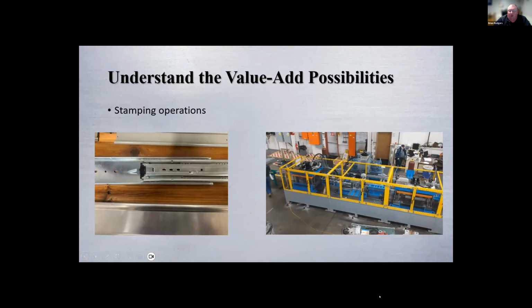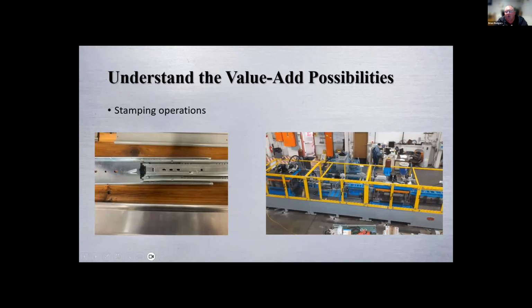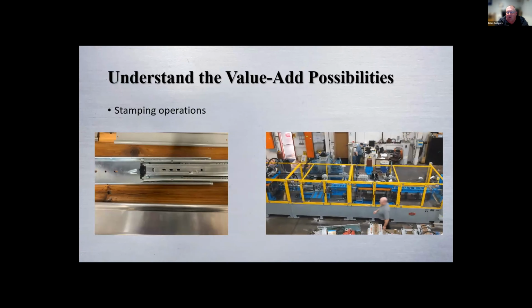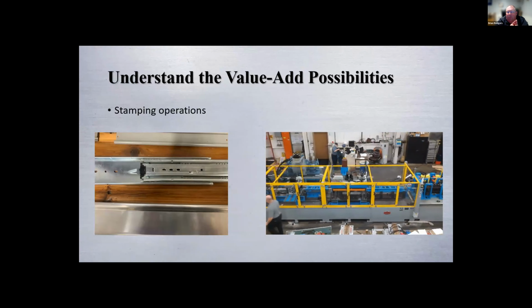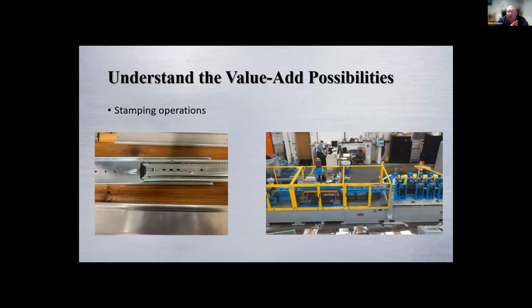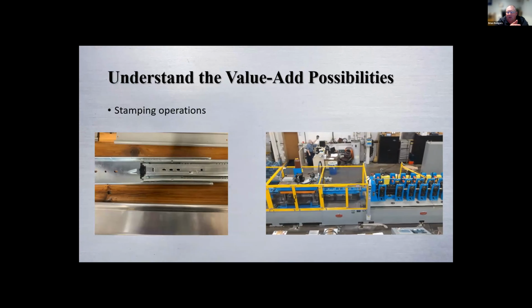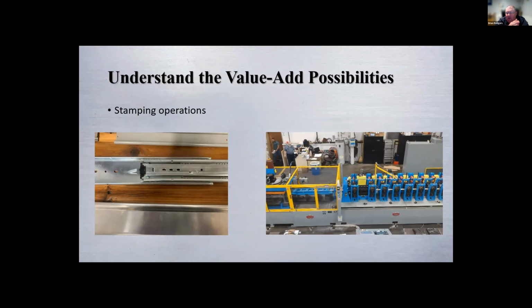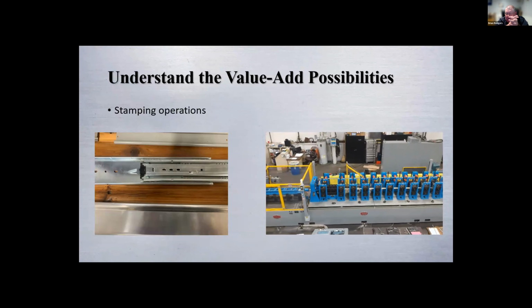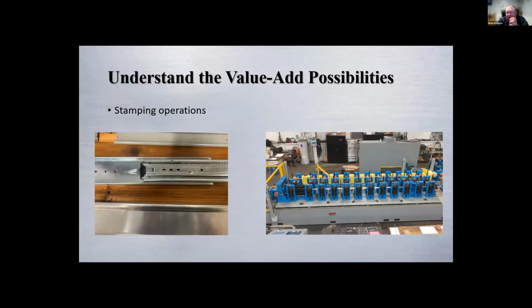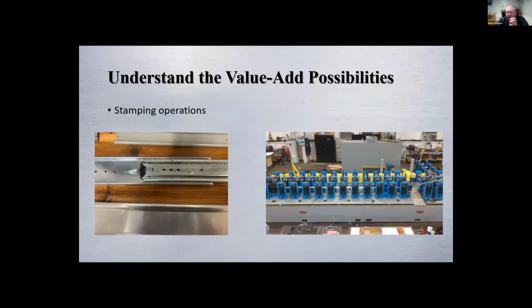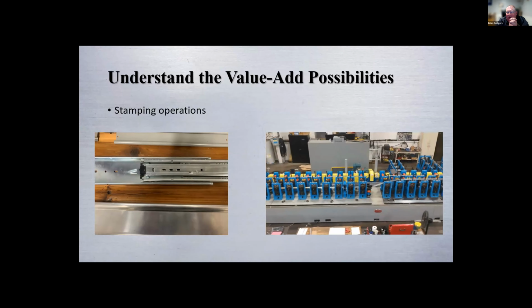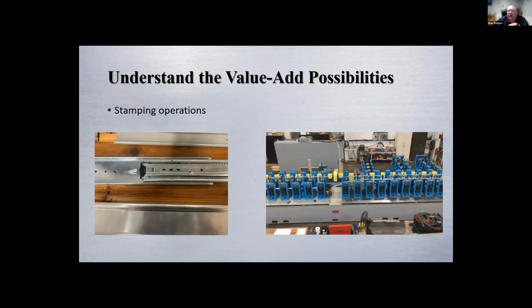But we can watch it. It goes through. You have a cutoff operation. This is what we call a post notch. So we actually are punching the part with 2 different presses on the exit end. And then as we're going through, you can see that the part was being manufactured from the roll former and a continuous coil. On this machine, it ran all 3 cross sections.